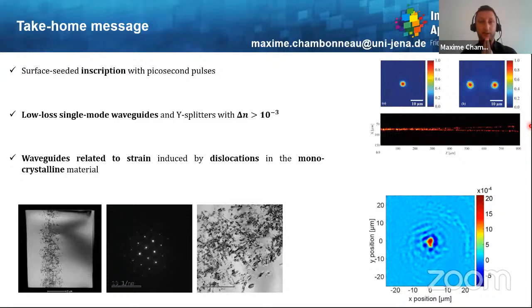Here is the take-home message for that part. With surface seeded inscription, we could write low loss single mode waveguides with picosecond pulses, as well as Y splitters, with a positive refractive index change higher than 10⁻³. And the written waveguides rely on strain induced by dislocations in the monocrystalline material.